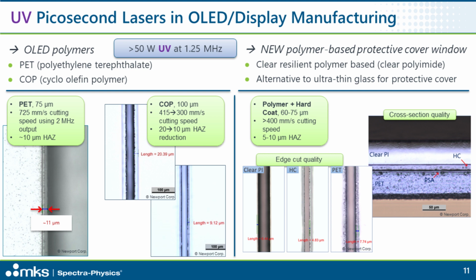COP is very good for polarization capabilities, and similarly, we show a high quality result. In this case, if you look in that little green box, we see that we were able to reduce a heat affected zone from 20 microns down to a 10 micron extent, and this came at a very small sacrifice in speed to achieve this 50% reduction.